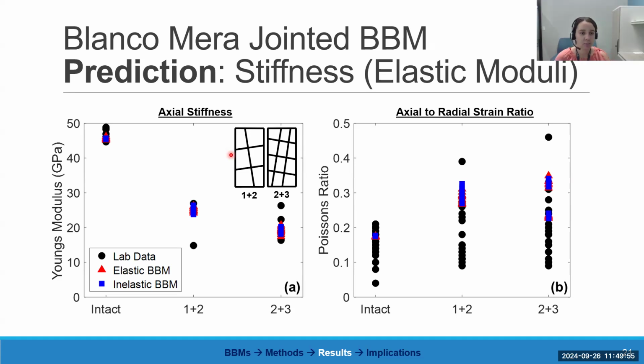Yeah, that's a good question. So that's part of the calibration process. The first thing that I found is best to start with for calibration is the stiffness parameters, because the stiffness parameters really only control the linear elastic region of the overall deformation of the specimen, the simulated specimen.